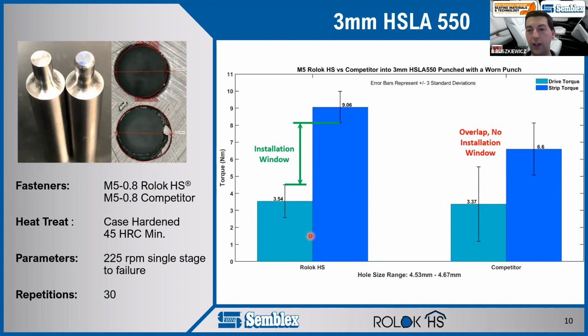When we look at Rolok HS's bars, we see that from the upper drive torque limit, which is about 4.5 Newton meters, all the way up to the lower failure torque limit at about 8 Newton meters, we're good. Any torque in that range will work pretty well. Obviously, we would recommend something in the middle because we will have some variability from the tolerances on our platings and our heat treatments and the fastener itself.